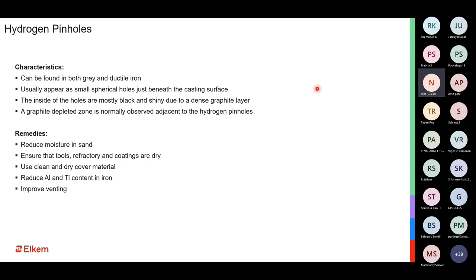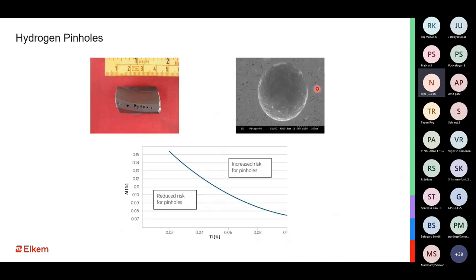And that is why we also have to see whether our venting process, the venting design or the vent locations, are sufficient and strategically placed so that you take care of all the gas which is emitted, should it somehow escape out of the cavity when the mold filling is happening. So this can be done for the hydrogen pinhole.